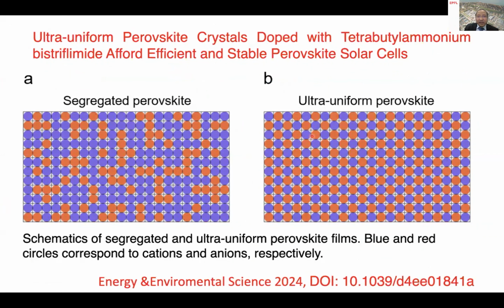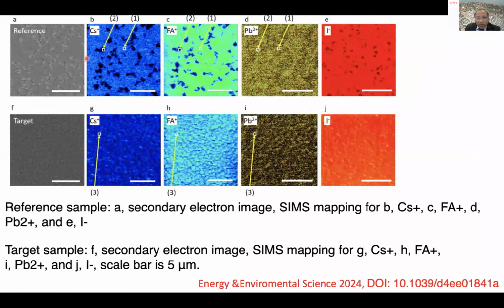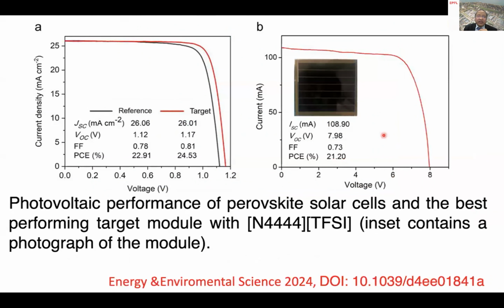Here we came up with another ionic liquid, a tetrabutylammonium trifluoromethanesulfonimide ionic liquid. By incorporating it into the perovskite solution, what you can see is, on the top, the control, where cesium is segregated, lead is segregated, and iodide is segregated. By using this ionic liquid, the cesium is uniformly distributed, and formamidinium as well as lead and iodide. So this is a very interesting approach where you can have a uniform distribution of the cations and iodides.